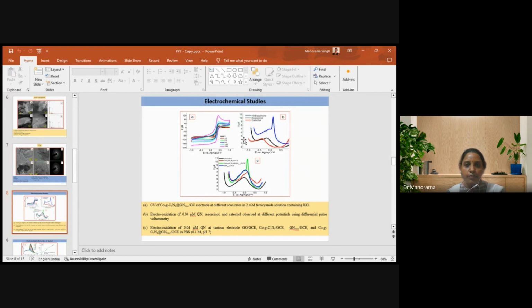Okay. So with the material, when we modify the glassy carbon electrode and we have taken the cyclic voltammetry, the cyclic voltammogram, then we have recorded this. Yes, the material is very much electroactive. When we increase the scan rate, at the different scan rates, the current increases from 5 to 200 millivolt per second.